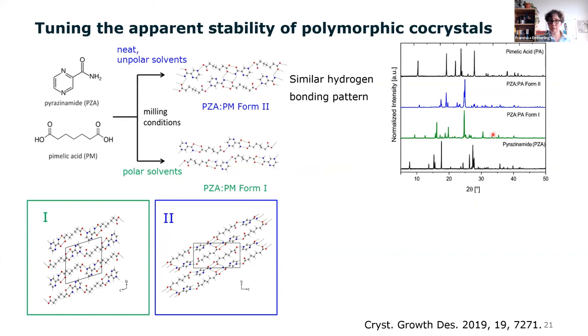Okay, we played around a little bit more with pyrazinamide, and here you see the co-crystallization with pimelic acid. Again, two polymorph forms, and interestingly, you can get form two under neat grinding conditions or with unpolar solvents. That is something we also observe quite often in this field, and you get form one when you use polar solvents. Again, we have similar hydrogen bonding pattern. We know from DFT calculations and also from slurry experiments that form one is the thermodynamically stable form. You see the crystal structures here.